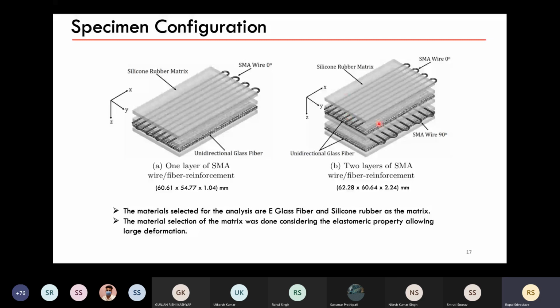I didn't mention before how we are actuating the shape memory wires: by connecting the two ends of the wires to a DC power supply. In the case of shape memory wires, the only important thing is to increase the temperature. We can use a hairdryer, a blower, a hot water supply, whatever. All we need is to increase the temperature so much that it reaches its austenite finish temperature and it starts bending or shrinking. In our case, we used a DC power supply, and by providing current, because of the resistance the temperature of the wires increased and we were able to reach the austenite finish temperature.